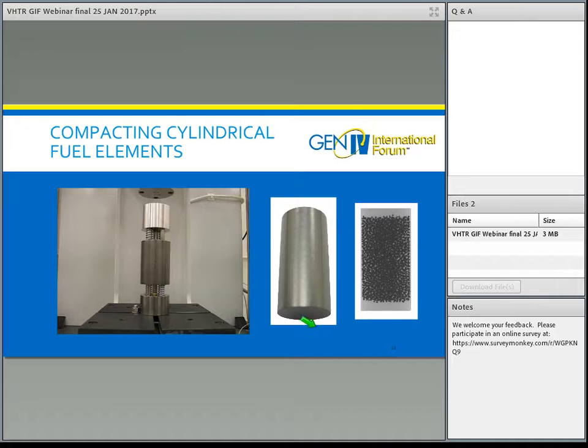So here we see inside a radiograph of a compact. Here are all the particles inside the compact with the graphite matrix surrounding them and separating the particles within that compact. The particles and the matrix are put into an isostatic press die that compresses them. They come out as a green ceramic material, which is then baked and made into the hard compact form that eventually goes into the reactor fuel elements.